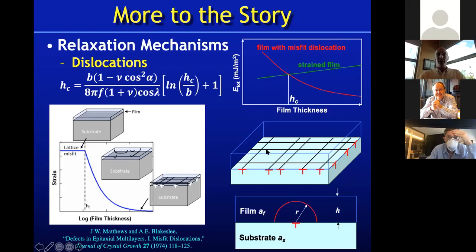Now, so here you see the energetics. I want to point out that we call this a critical thickness. It's common to be able to go beyond this critical thickness because there's an activation barrier to bringing in the dislocations. So yes, if you're at high temperature and dislocations can nucleate and move around well, then you'll get closer and closer to this equilibrium critical thickness. But if you're at low temperature and you're in a system where it's hard to bring in dislocations, then you can typically go beyond this equilibrium critical thickness. And if I show what really happens in films, so here as a function of thickness, when one gets beyond the critical thickness, now it's energetically favorable to have dislocations there, but one needs to nucleate them.